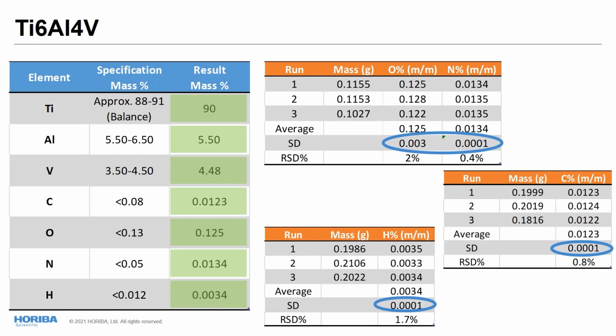XRF results, but also elemental analyzers results at the same time. And again, even on low ppm values or high percent values, you can see very good standard deviation, very good accuracy of the inorganic elemental analyzers with about 1 ppm standard deviation at a level of 34 ppm of hydrogen.